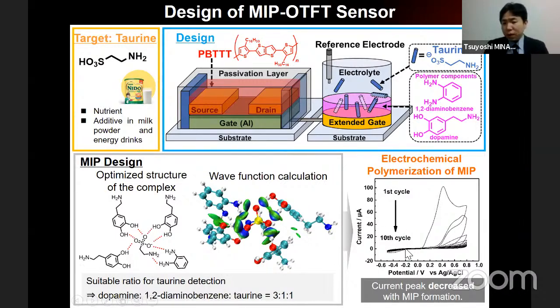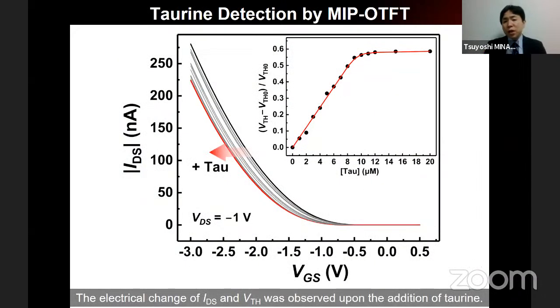After we polymerize the compound, as you can see, the cyclic voltammogram showed very significant changes. So we could say that we functionalized the MIP on the extended gate electrode. Actually, we have data based on AFM and so on, but today I have no time to explain in detail. We already characterized the electrode by using a microscope and an electrochemical measurement system. After this, we decided to detect taurine.